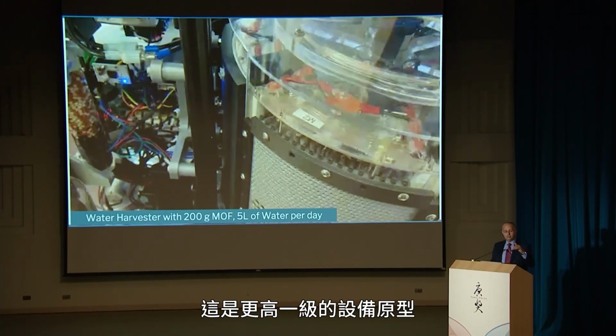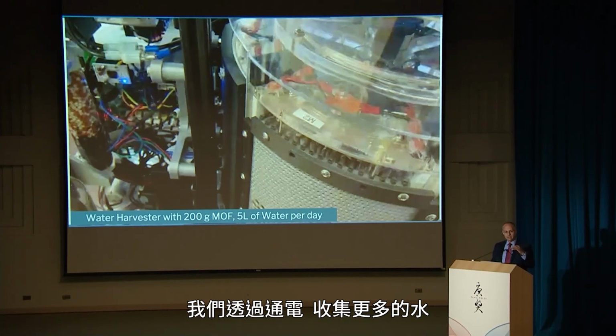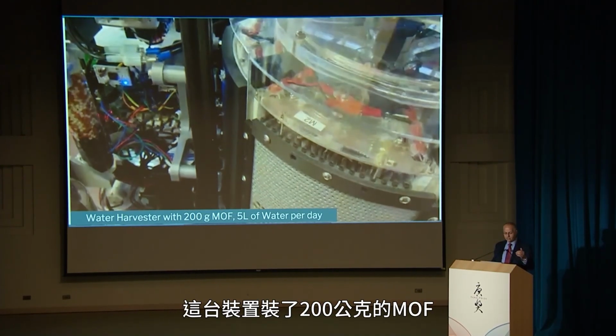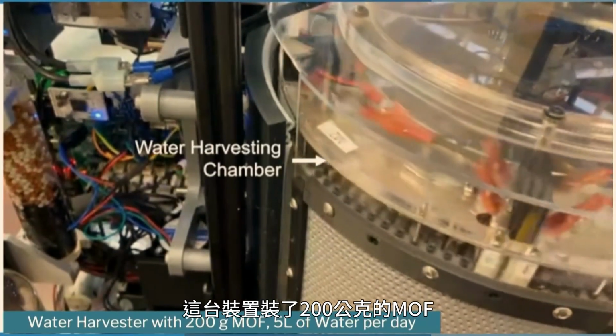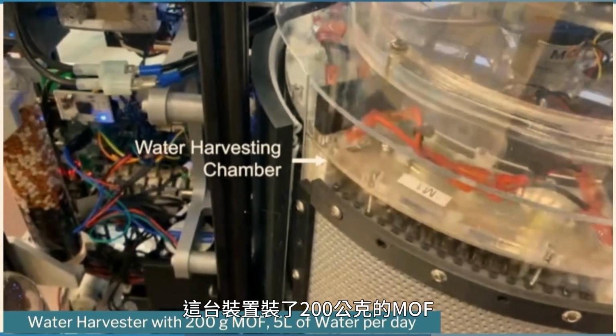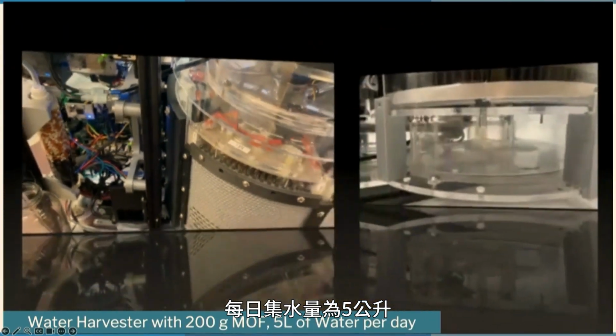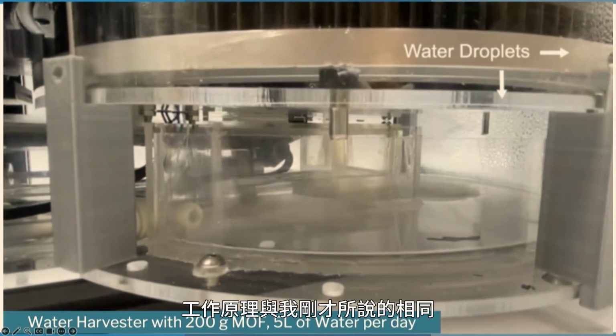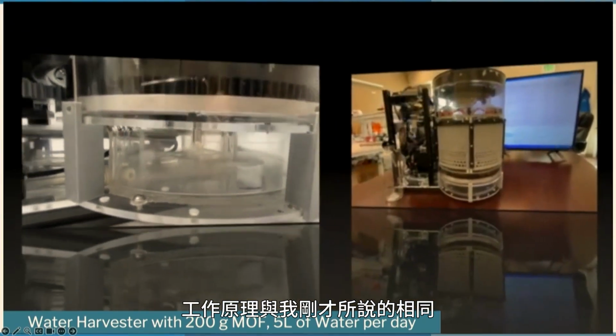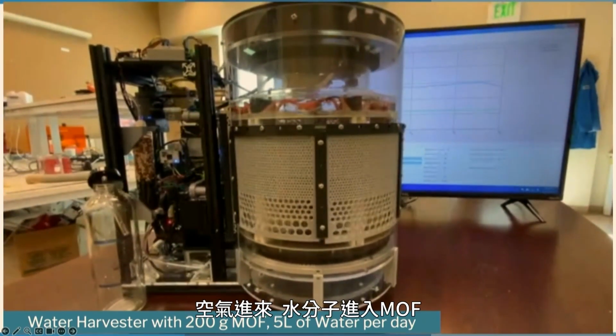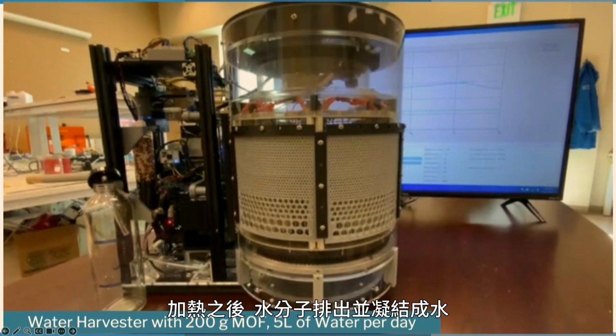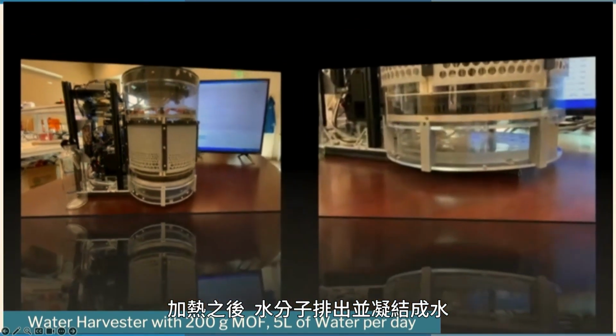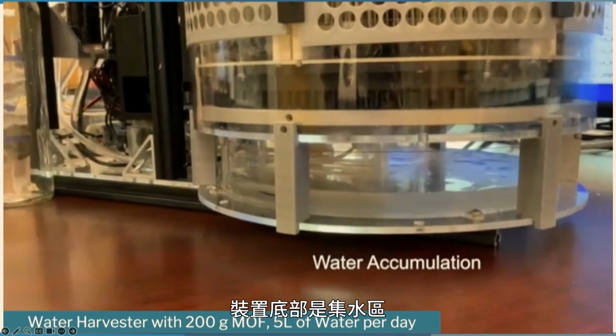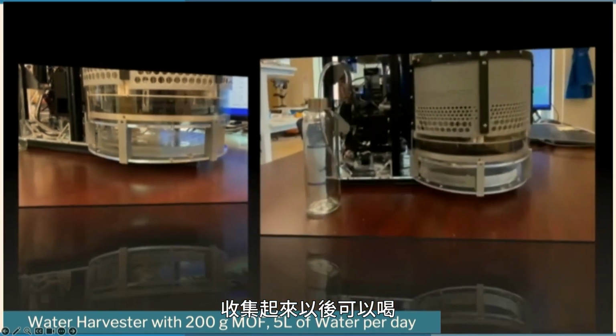But here's the next level prototype. Now, we electrify the system so that we can make more water. So this device is equipped with 200 grams of MOF, and it gives you 5 liters of water per day. And it works on the same principle I just described. Air goes in, water goes into the MOF, you heat up the MOF, water comes out, it condenses. There are puddles of water at the bottom. And then you can collect it and drink it.